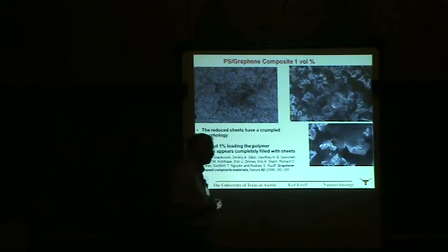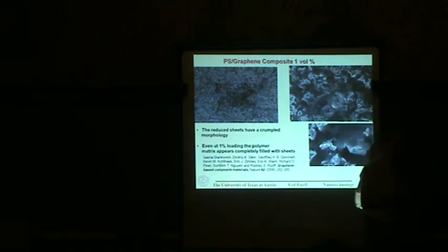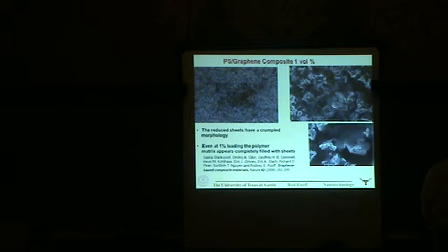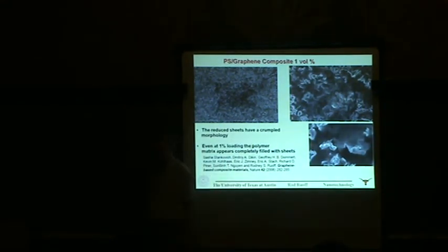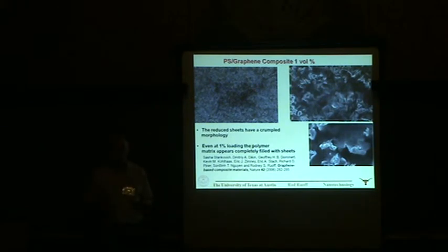I told you this morning that you couldn't as easily get graphite itself to fall apart into individual layers as we can graphite oxide. Graphite oxide very easily falls apart into individual layers in water and aqueous suspensions. But progress has been made, such as by Johnny Coleman's group at Trinity College in Dublin. So one can work hard and get some exfoliated graphene and multi-layer graphene from graphite itself. And Alexander Balandin reported at a weight percent loading of 5%, they had pushed the thermal conductivity of an epoxy composite to 7 watts per meter Kelvin, which is quite amazing.